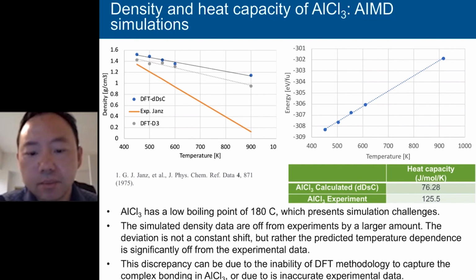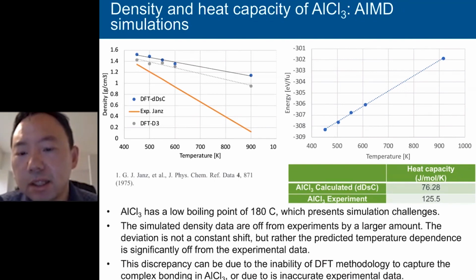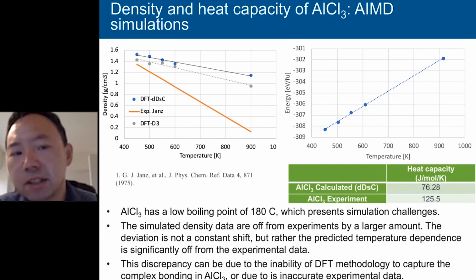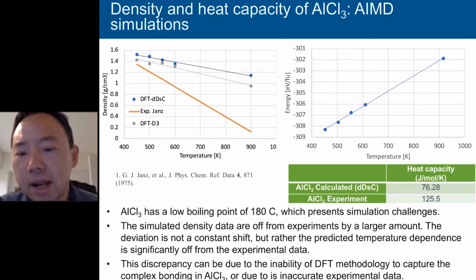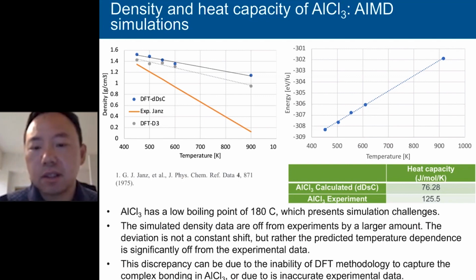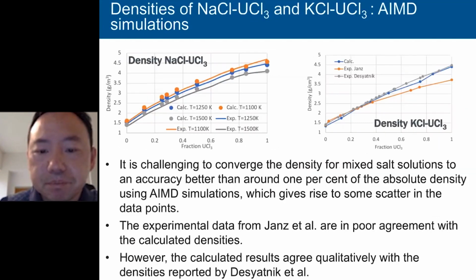This can be either due to the inability of the DFT method to capture the chemical bonding of the aluminum chloride, which I'm going to mention shortly, or due to inaccurate experimental data. So David's suggestion is that we should look at this discrepancy more closely in the future. Also, if you look at the table, the Ab-Initio calculated heat capacity is also very different from the experiment. This discrepancy must be addressed to help us better understand why we have such a huge discrepancy between modeling and the experiments.